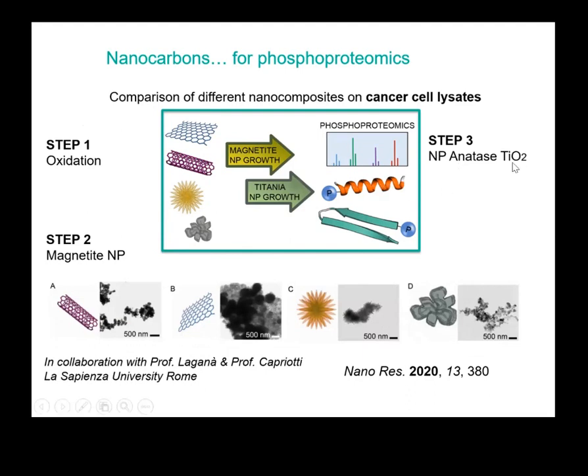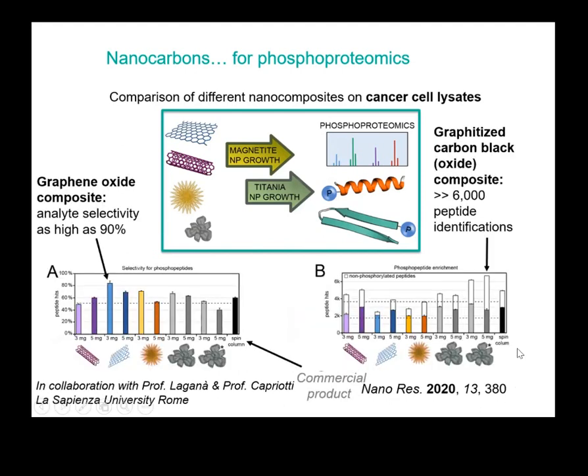And then in the consequent step, we grew nano-sized titania, and that's where we really saw different templating effects played by the nanocarbon scaffold. And these were also reflected in the performance of the resulting nanocomposites. So for instance, the graphitized carbon black allowed for the highest number of peptide identifications. But in terms of analyte selectivity, especially peptides as opposed to phosphopeptides, because through the purification process, the preparation of the biological sample, it is possible to separate other fractions containing lipids and DNA. So really one of the key issues is the separation between phosphorylated and non-phosphorylated peptides. So in this regard, the graphene oxide had the best performance.